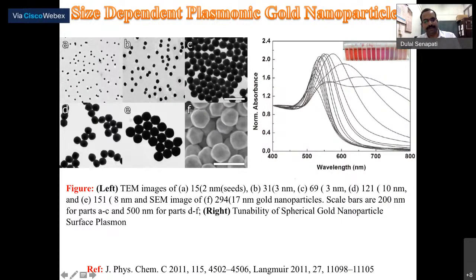We are simply changing the diameters from A to F, where A is only 15 nanometers. And F is how much? F is 294 nanometers. So it's almost a 300 nanometer difference in dimension. See how nicely we can tune their absorbance from 500 nanometers to almost 700 nanometers, because their absorbance is shifting towards the red.